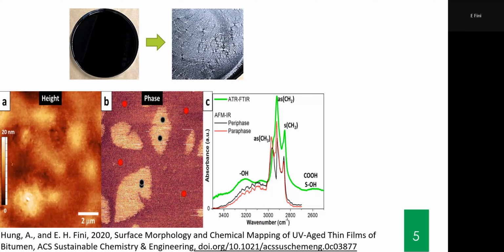So in case you age the sample and then start doing, for instance, a DSR test or bending test, tensile test, what are you really testing? Are you testing the top layer or the bottom layer? Maybe the very bottom layer, if you have a thick sample of 1 millimeter or more, is not even aged. So what you're really measuring at that point, when you mix the whole aged sample and start doing tensile or bending, all those tests, maybe you're just measuring an average of aging. The top layer is pretty aged, the bottom layer may not even be aged. So now you're mixing the whole sample, you're going to get an average, which is literally lower than the real aging level on the top.